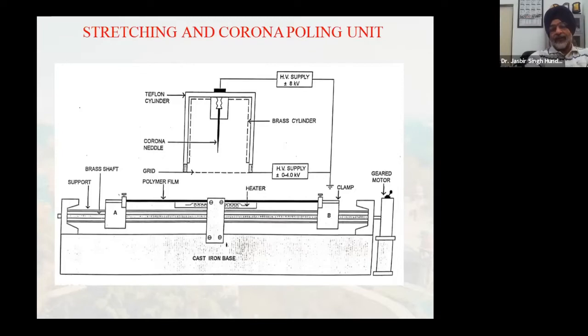Okay, and what we find here is when the film is hot, the dipoles are more mobile. Simple logic is that when the film is cold, and if you apply field across the film, the dipoles will not be able to move much at room temperature. But when the film is heated, the dipoles would be able to move because thermal energy will assist the motion of the dipole. They will get aligned in the direction of the field.